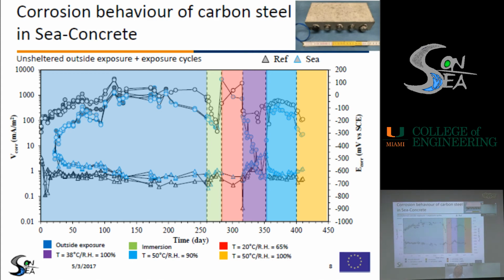Then we have a further increase in the corrosion potential due to the drying of concrete, and then we had some fluctuation due to the change in the environmental exposure. We do not have significant variation of either corrosion potential or corrosion rate, indicating that in all of these exposure conditions, passive conditions were maintained on the carbon steel bar, which was expected since no chloride was present.